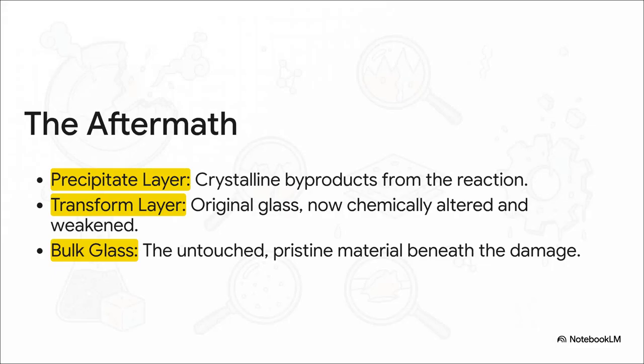So if we were to break down what we're seeing here, you've got these layers of damage. Right at the top, that's the precipitate layer, those new crystals. Just beneath that, you have what's called the transform layer. That's the original glass, but it's now chemically altered and super weakened. And then finally, deep below all that chaos, the bulk glass is still pristine, completely untouched.